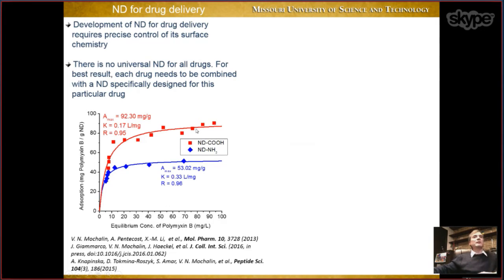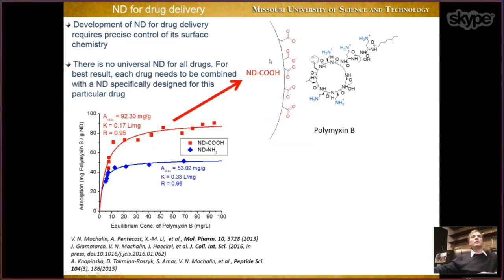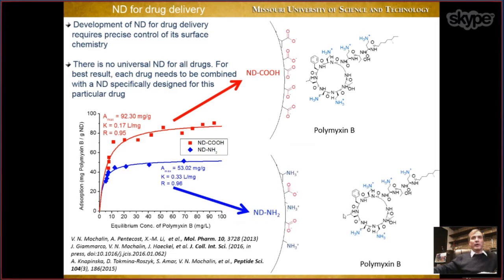Of course, if you want to implement this material in any clinical environment, you have to pay attention to things like this. And in this particular case, it was easy to explain because carboxylated nanodiamond has negatively charged carboxy groups when you place it in water environment. And this is polymyxin B, which has a lot of NH3 plus groups. So there is electrostatic attraction between nanodiamond and this molecule. This is why you have higher adsorption capacity. In case of aminated nanodiamond, now you have some amount of amino groups on the surface, and then they repel positively charged polymyxin B. So you have less adsorption capacity. So again, one has to pay attention not only to toxicity or non-toxicity of this material.